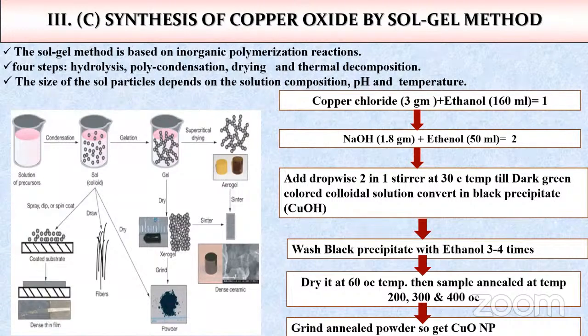As shown in the flow chart, initially I am taking the copper chloride, 3 gram, plus the ethanol. Then NaOH is added, plus the ethanol. Then all these are added dropwise and stirred at 30 degrees temperature till the dark green color solution is converted to a black precipitate. Then this black precipitate is washed with ethanol 3-4 times.